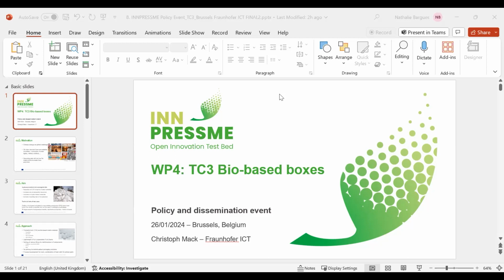VTT provided some fibers, nanofibrils from cellulose. INN-PRESSME provided fibers made from flax and hemp, and in this case, it was microfibers. Both these were then incorporated into PLA to act as a reinforcement agent. The fibers were characterized in these compounds with regards to the fiber nature, the fiber treatment, the fiber concentration, and their influence on its properties. In the end, we can state that all tested fibers act as a reinforcement agent, especially with regards to the material rigidity. In the end, one material composition was chosen for the demonstrator.